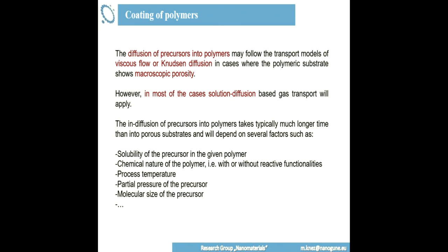So the point is that you cannot, in this situation, consider Knudsen diffusion, of course, as a main issue. Knudsen diffusion could be considered only if your polymer substrate has pores. That means if it's a sponge. But if it's a bulk polymer, you need to really think about this solution diffusion mechanism. And there you need to consider several physical chemical parameters, for example, the solubility of the precursor inside of the polymer. You need to consider the chemical nature, process temperature and so on. So many factors which you know from physical chemistry. Most of you are chemists or you have studied physical chemistry as well. And you pass through all of those issues in terms of calculations and model setting up.